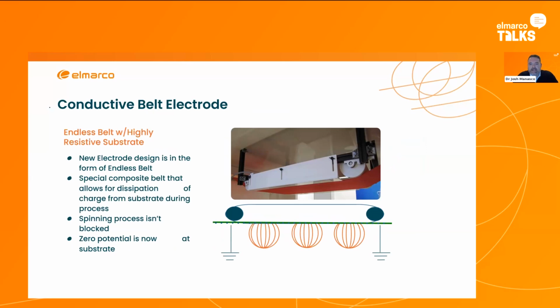But in this case, it enables us to spin on thicker materials that weren't possible with the standard wire collecting electrode. And it allows us to have some flexibility with different types of substrates that might be useful in other applications. We don't normally have any issues with spun bonds or melt blowns, for instance, but there can be some films or other things that are resistive, or very thick nonwovens that can be difficult to coat.